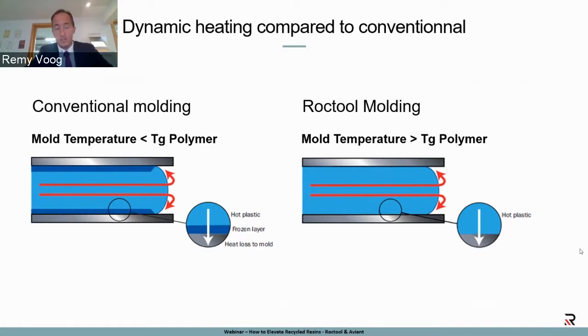The second issue that you may face is more mechanical. The flow of this vein of resin through the mold is somehow accelerated, and therefore you're going to have an alignment of the polymer chains in the direction of the flow, which will create anisotropy. Most of those issues we tend to solve in Roctool by not having this frozen layer. Therefore, you will eliminate the weld lines. You will have a resin-rich surface, which avoids visible fiber at the surface. And you will have time in the process, which we're going to see later, to realign and relax the polymer chains in order to decrease the anisotropy and therefore the molded-in stress.